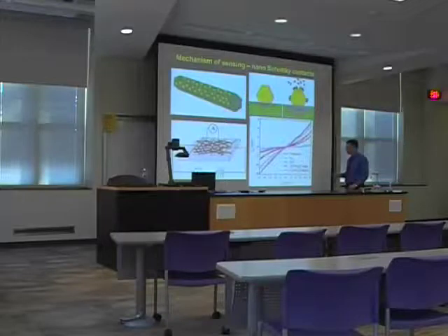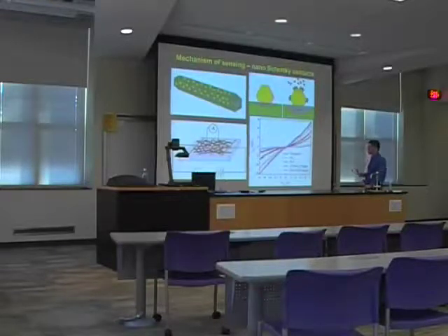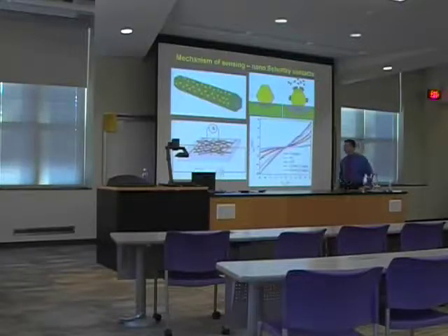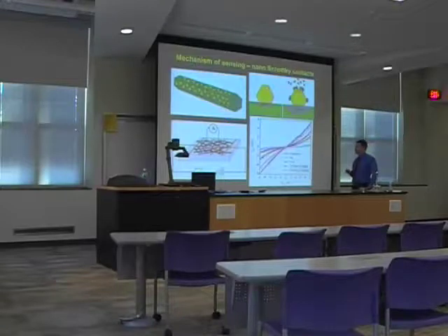However, if you add water to carbon monoxide, you will get analog sensing, not digital, which means that as you add more and more water, you will see higher and higher drop in conductivity, which means that you observe additional effects, not just adsorption.